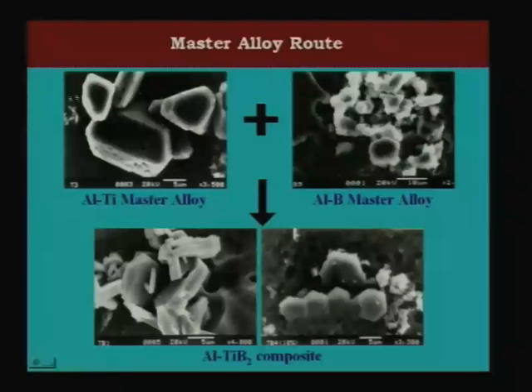In the master alloy route, you take an aluminum titanium master alloy with Al3Ti particles shown here, and an aluminum boron master alloy containing the AlB2 particles, put them together and react them to get TiB2 particles. These TiB2 particles are hexagonal in structure and give you very high strengths, and that is what is called the master alloy route.